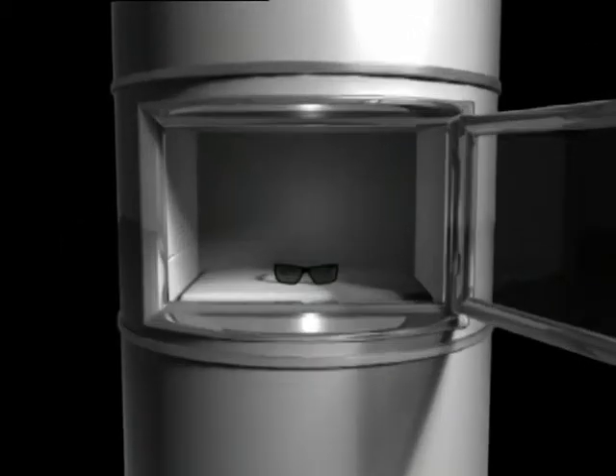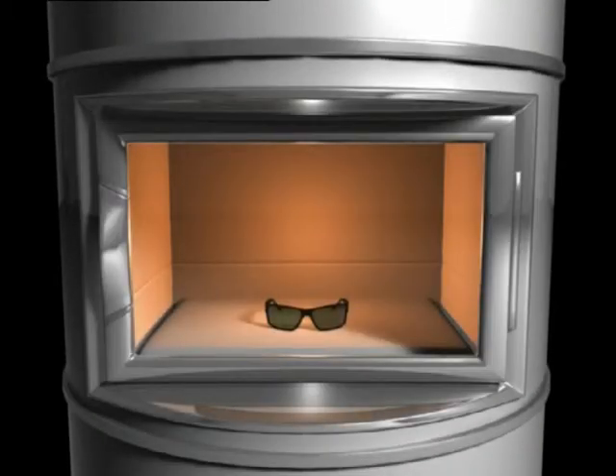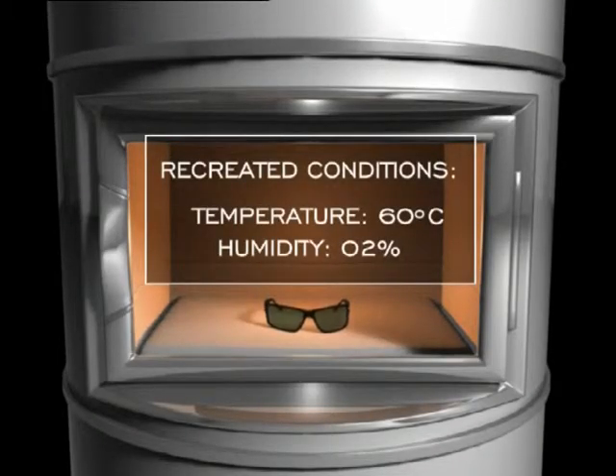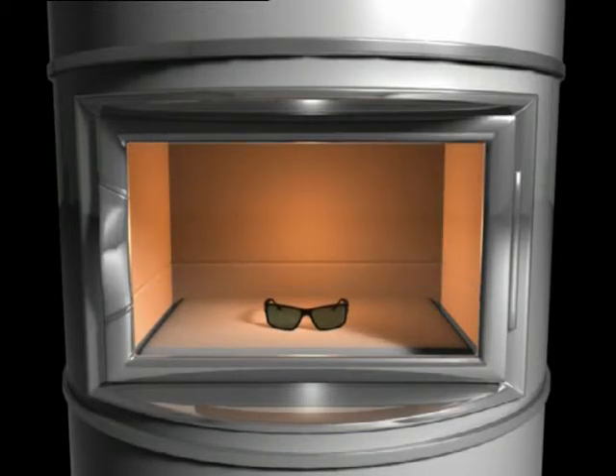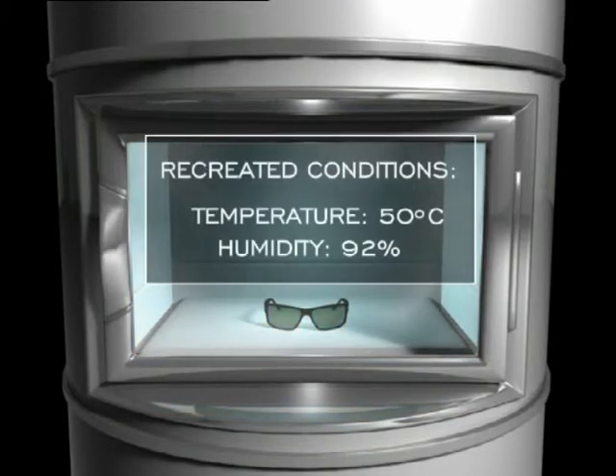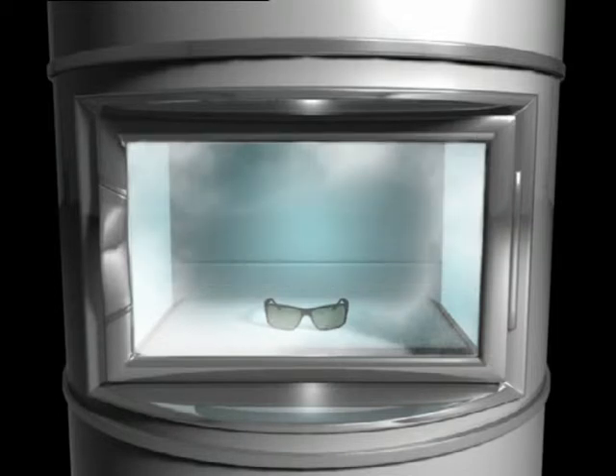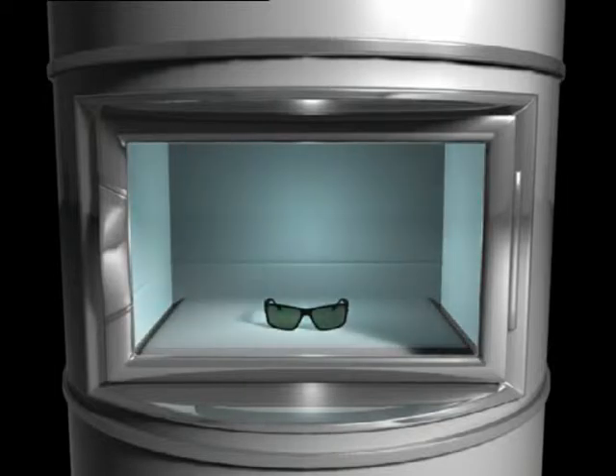Accelerated aging test. This is an additional Luxottica test made beside the standard ones required by current laws. The paints and colors of frames are damaged by temperature, humidity and UV rays. The objective of the test is to verify the duration of the frames by subjecting them to 4 hours under UV rays at a temperature of 60 degrees centigrade and 4 hours of condensation, humidity 90 to 95%, at a temperature of 50 degrees centigrade. This treatment is repeated several times.